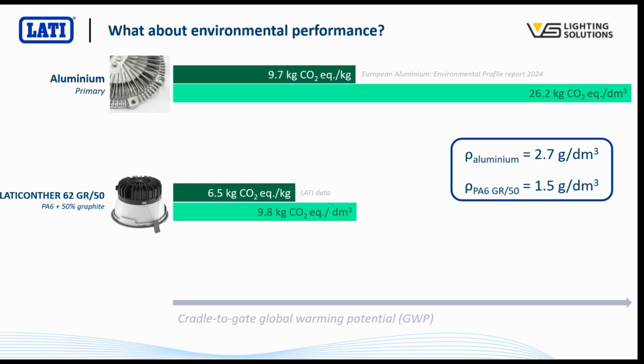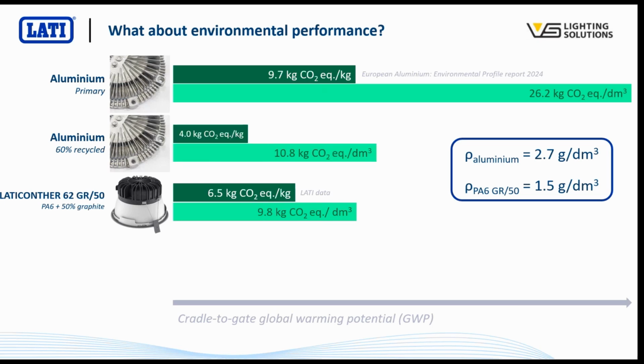And at which point you might say, well, that's great, but nobody uses primary aluminium. Everybody uses some recycled content in there. Okay. But even if we allow for, let's say, using up to 60% recycled aluminium, we still see a reduction in GWP for the plastic versus the aluminium version. And remember also that this is just cradle to gate, so we're not considering any of the processes that happen further downstream. So before we consider the fact that the energy consumption associated with injection molding, where we're running machines at maybe 250, 300 degrees C and running tooling at 90 degrees C, is going to be much lower than for aluminium die casting, where we're melting materials at maybe 700 degrees and we have mold tools that are set at around 400 degrees.